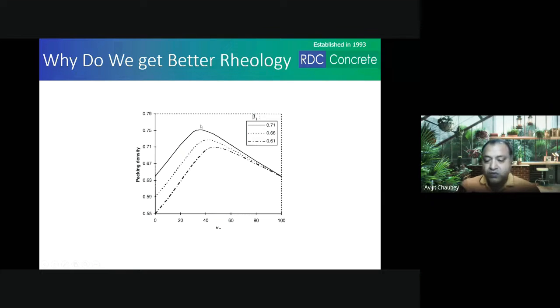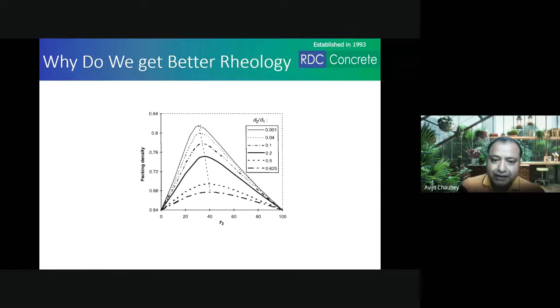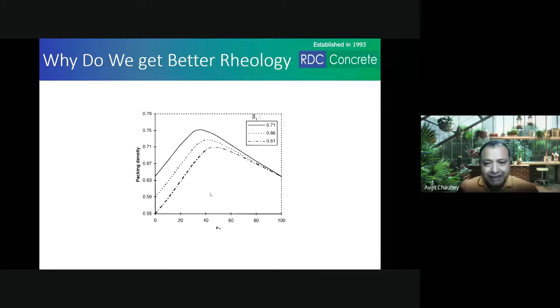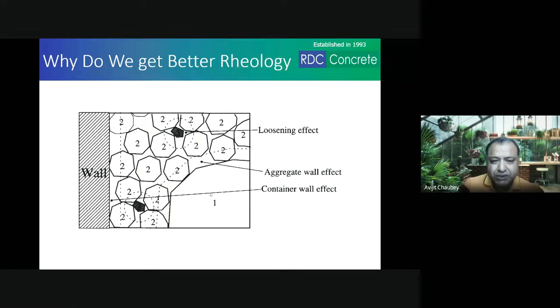So the first thing that is affecting the particle packing is the proportion of the sizes of the aggregates that you are mixing together. The second thing is the packing density of the material, the quality of the shape of those materials that you are using for packing these aggregates together. And the reason this works is because of two effects called the loosening effect and the wall effect.